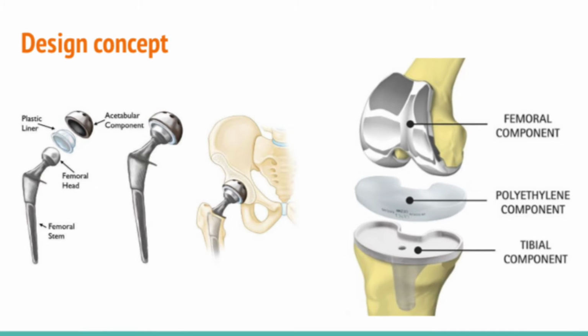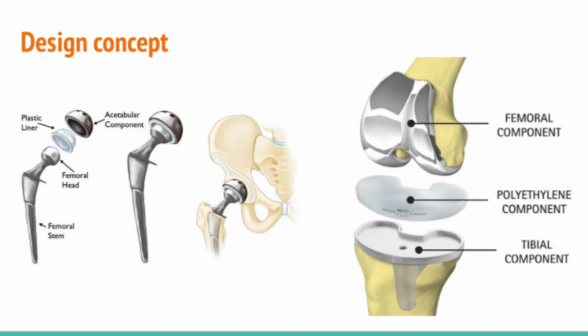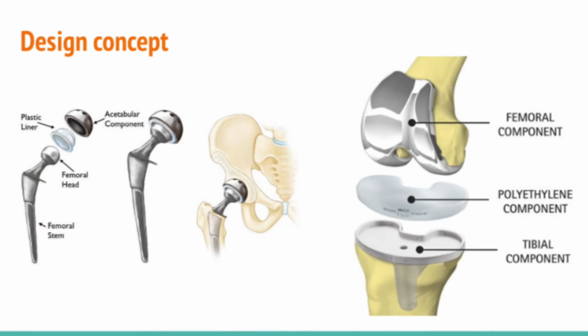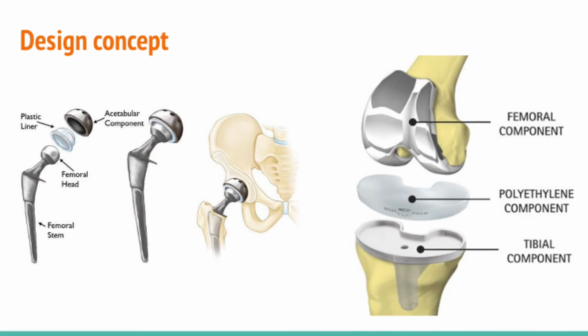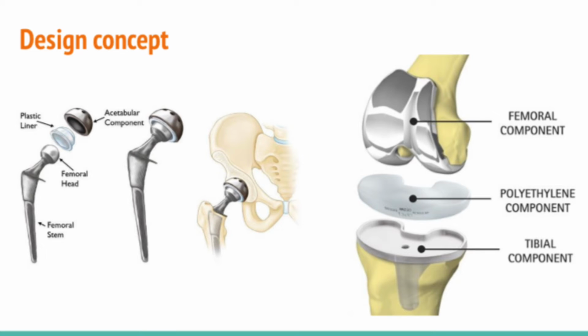A knee replacement is also made of 4 parts. There is the femoral component on top and the tibial component on the bottom, which will hold the liner. There's also the liner in the middle that will serve as the new cartilage, which is made of polyethylene. Some doctors will also add in a new kneecap or patella. It is made of metal and the underside is covered in a piece of plastic to prevent metal on metal wear. If you look at the complex shape of the knee and implant, it can be seen why a ceramic implant would not be favorable. The shape is too complex for the quality of the implant to be better as a ceramic than a metal. Also, the ceramic would be too likely to fracture in a knee.